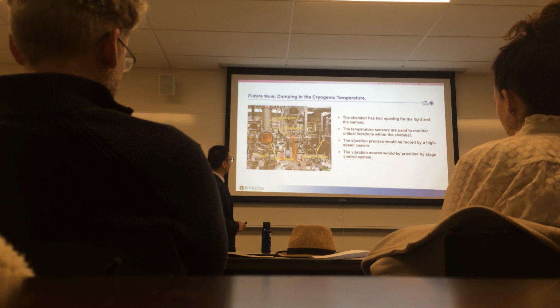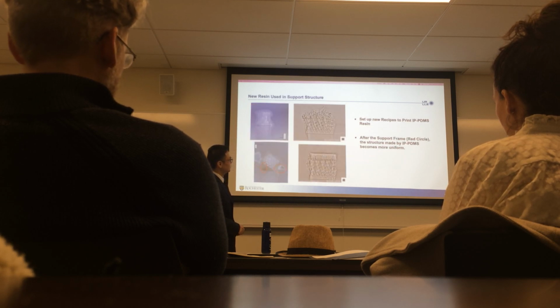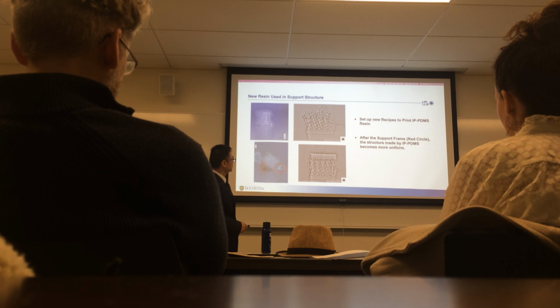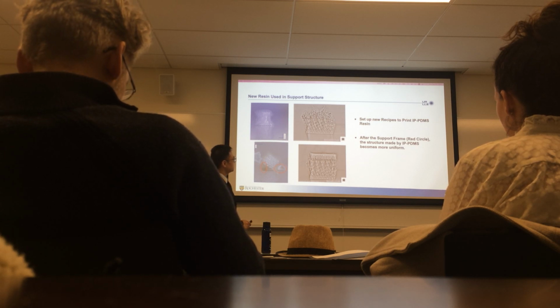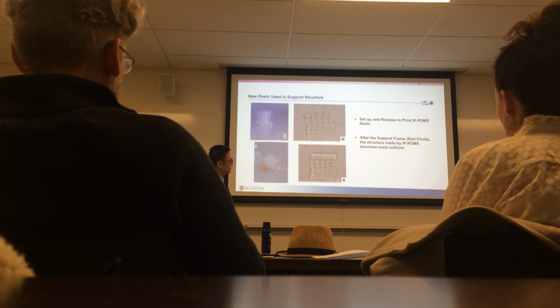Another future work is that we want to use a new resin to manufacture our foam structure. The new resin has very high elasticity, so it can hold more force and has high energy dissipation abilities. But there are problems printing these foam structures. If we use the original recipe to print these structures, we get a series of shrinkage problems. But when we set up a new recipe for the new resins, we can add some support structures for the foam structures. This will help our structures with the new resins become more uniform.